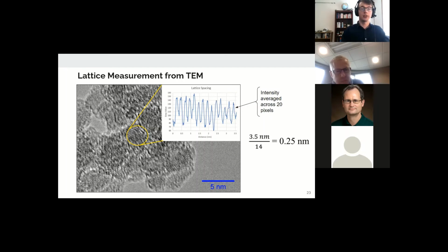So this image gives insight into our TEM analysis technique. The yellow ring around a nanoparticle displays the size measurement, and the inset graph shows the gray intensity of a line drawn through the nanocrystal perpendicularly to the lattice planes and averaged across 20 pixels.